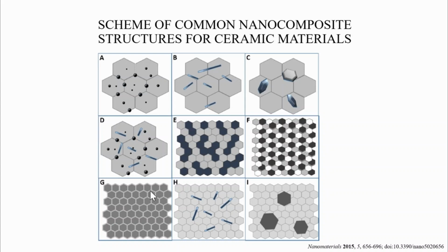Figure G demonstrates a nanocrystalline composite with grains of a single phase separated by grain boundaries with a different chemical composition, a second phase. And finally, figures H and I exhibit nanocrystalline composites featuring elongated grains or plates of one phase embedded within the nanocrystalline matrix of another phase.